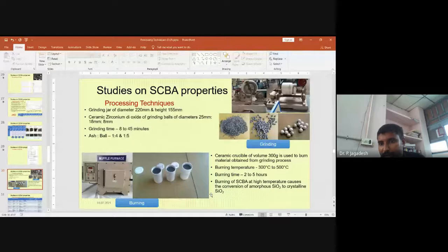If you see the right side, grinding balls with different diameters are used: 25 mm, 18 mm, and 8 mm. The type of ball used is ceramic, zircon ball, used for grinding. The grinding jar is of diameter 220 mm and height 155 mm.